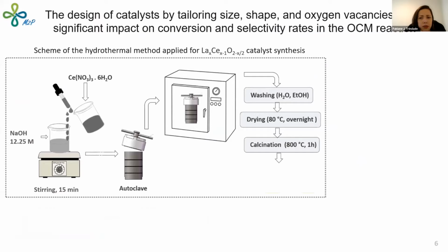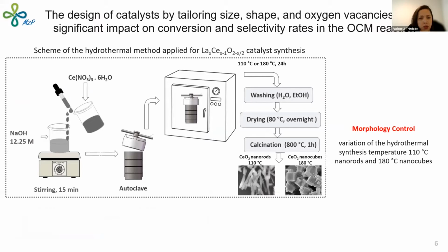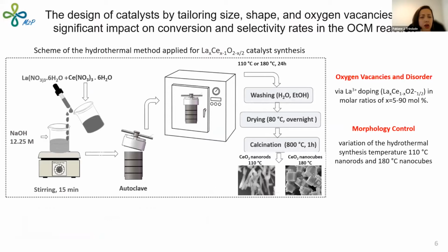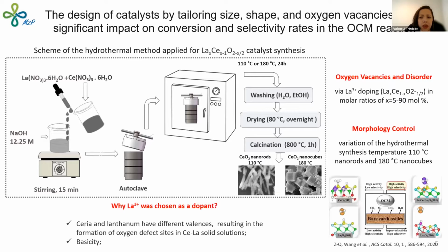In our work, we produced controlled catalysts, nanorods and nanocubes, by a hydrothermal method. To control the oxygen vacancies, we doped these catalysts with different ratios of lanthanum. Why did we choose lanthanum as a dopant? Ceria and lanthanum have different valences, so this results in defects in the Ceria-lanthanum solid solution. Also, lanthanum has a good basicity, which is really important for the OCM reaction.